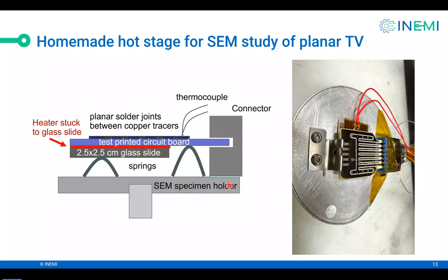So we have, let me describe the cross section on the left. The daughter card, the test circuit board, is plugged into a connector. So we make electrical connections, also mechanical connections. And this daughter card, of course, has the planar solder joint in the top, shown by the black line. We connect a thermocouple to measure the temperature of the circuit board. Then this red feature is a Minco mini heater, very thin heater. So you can heat the circuit board and the solder. And below that is a glass slide, and we push with the spring.